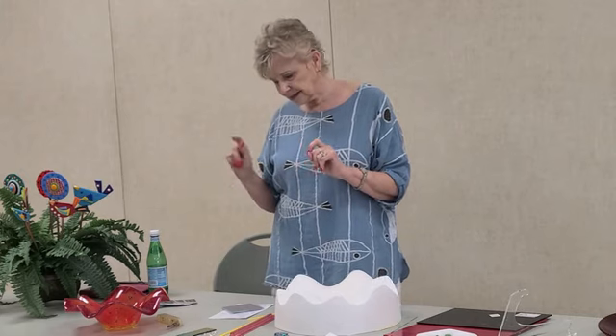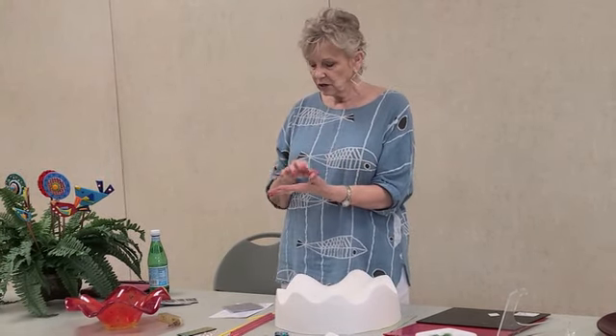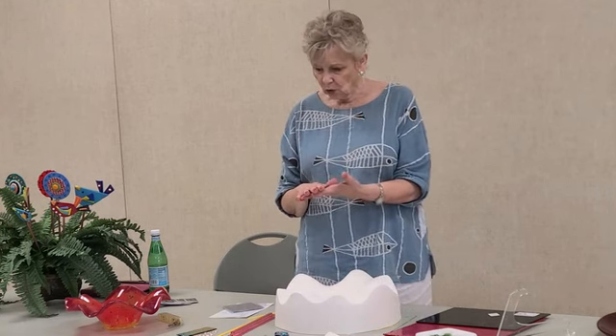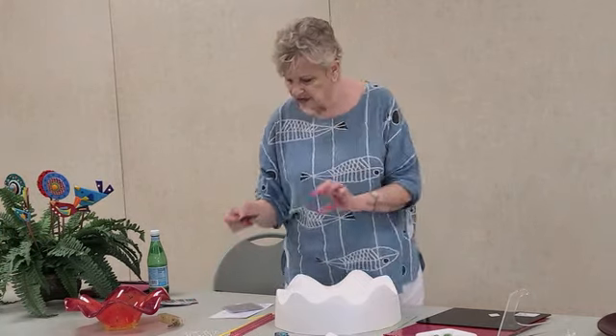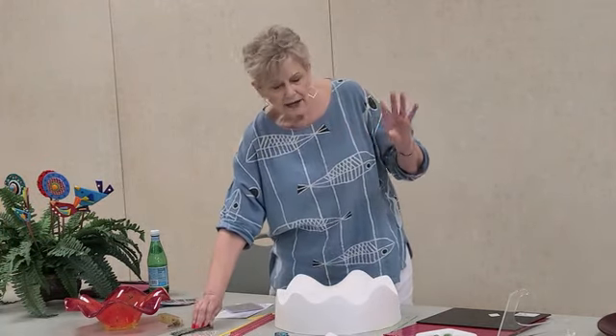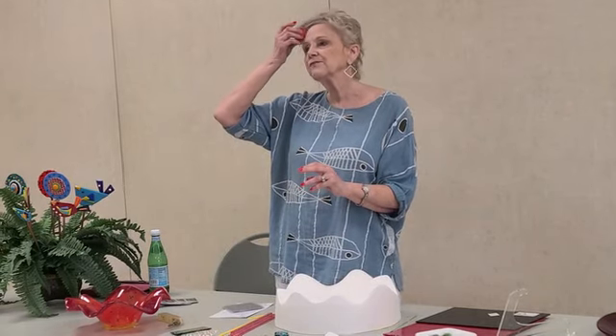Copper oxides and copper carbonate. You can sprinkle between the glass. It will turn the bubbles turquoise, really pretty. You'll get a lot, I mean like tons of small bubbles, kind of like these, but maybe even smaller. And so I made those on purpose.